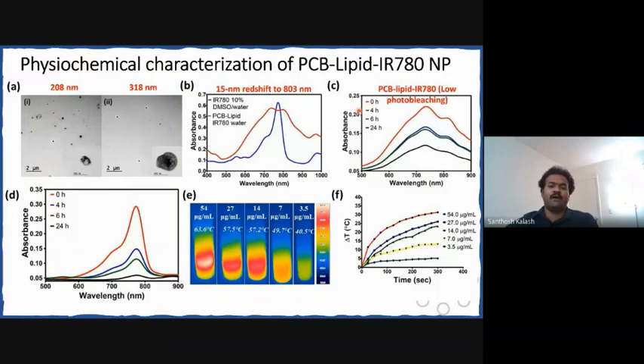And a more important part of this study is also to check the stability of the nanoparticles and how they can protect the dye from the light. So what we did is we incubated the nanoparticles in open daylight for 24 hours, and we checked the absorbance. You can see here that IR780 alone is getting degraded and its absorbance is reducing drastically within 24 hours. But coming to the lipid nanoparticle formulations, you can see that they still have some absorbance retained by the material, which means that the degradation happens, but at a very slow rate compared to the free dye.